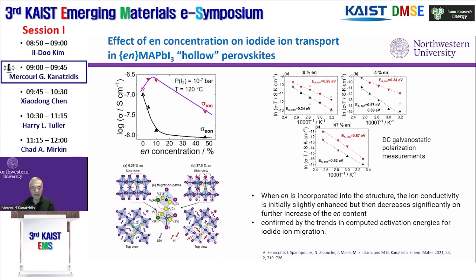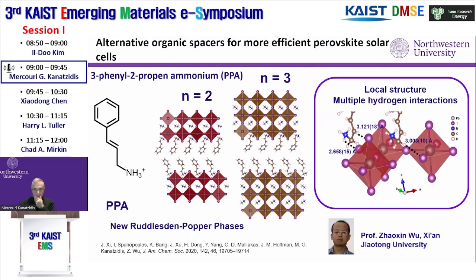So in other words, the ethylene diammonium cation and the vacancies frustrate the ion migration and raise the bar, raise the activation energy to slow them down. So this is quite interesting. And we were able to make stable tin-based solar cells that were actually at the time record breakers, about 7%. So back to the 2D perovskites.